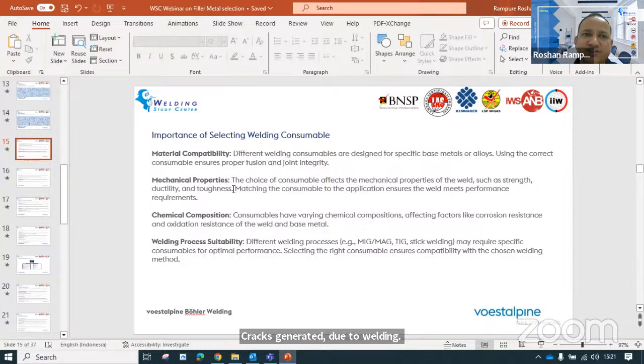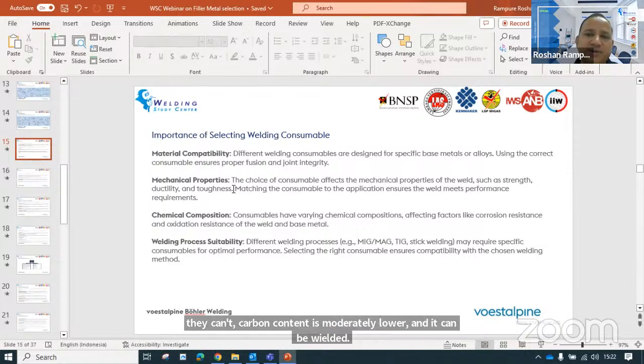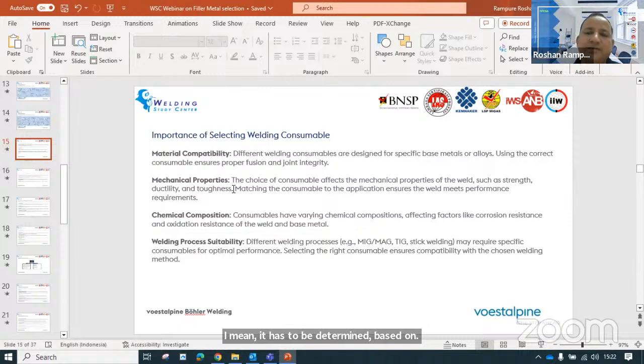So in order to avoid such failures, first you have to do the chemical analysis of the base material, to determine what are the constituents or composition of the base material. If the carbon content is very high, then generally it is not recommended to weld such material. If the carbon content is moderately lower and it can be welded, it has to be determined based on the calculation of carbon equivalent. So if the carbon equivalent is manageable on the higher side, then a slightly higher preheating temperature is recommended, and maintain a slightly higher interpass temperature so that cracks may not be generated. So these are the possibilities. There are certain specialized electrodes also available, which can be used for joining or welding of such unknown material.